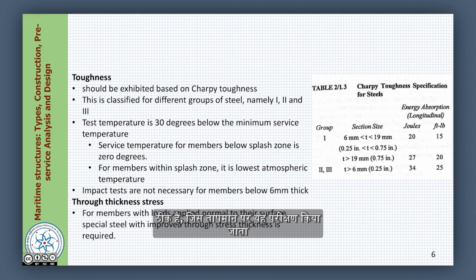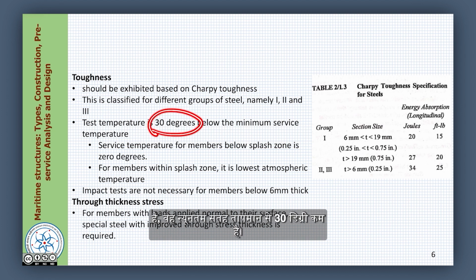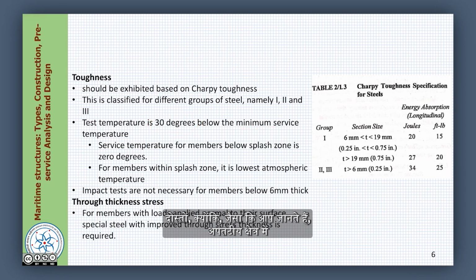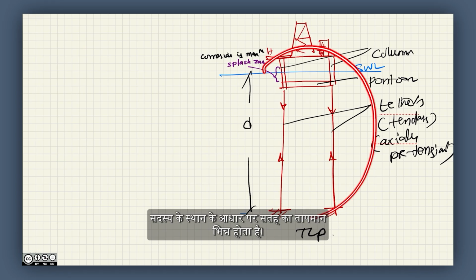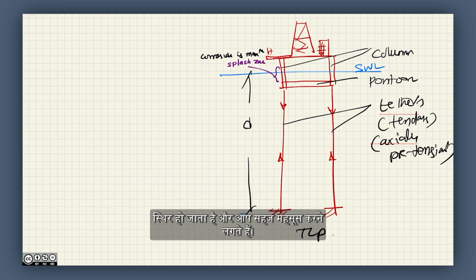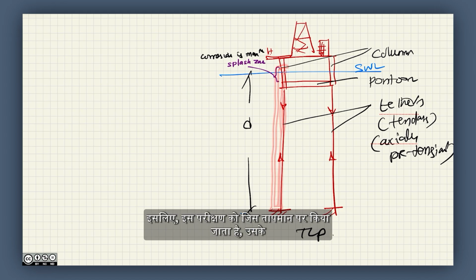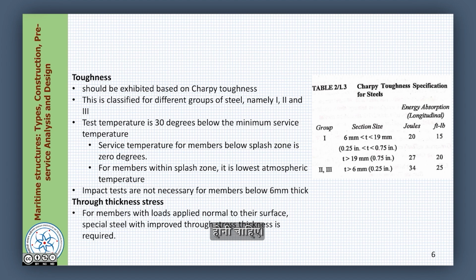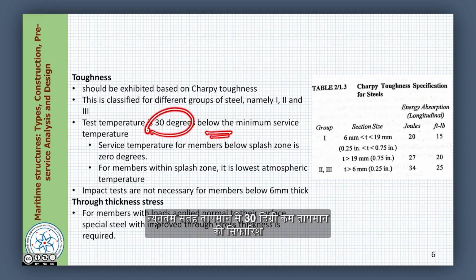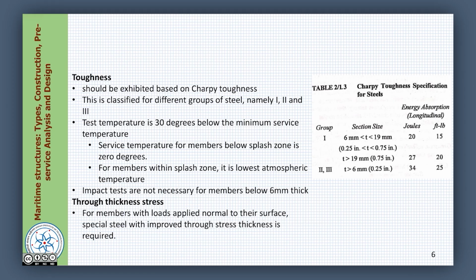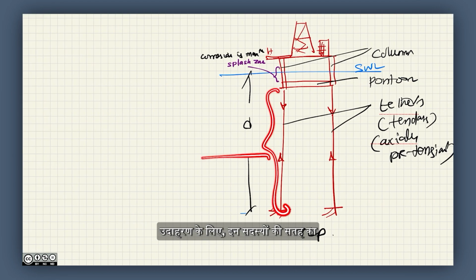However, friends, you conduct Charpy's test at a specific temperature. The test is conducted at 30 degrees below the minimum service temperature, because the service temperature varies depending upon the location of the member in offshore. As you go deeper, the temperature freezes. As you go above, it becomes relaxed. So, the members are subjected to differential temperature as well. So, one must be very clear in ascertaining the Charpy's impact or Charpy's toughness based on the temperature at which this test is conducted. International codes of practice for design recommend temperatures 30 degrees lower than the minimum service temperature to which the member is subjected. For example, the service temperature of members below the splash zone is 0 degrees. For example, these members, the service temperature is 0 degrees.